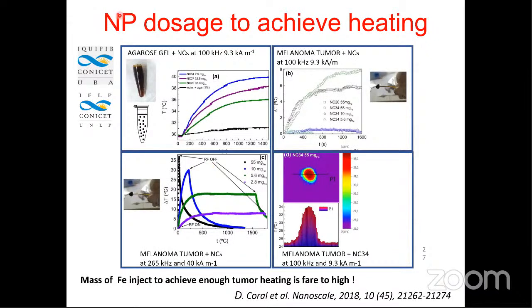And what we found is that, for instance, if we have an agarose gel with 2.3 milligrams of iron, we have a very nice increase of temperature. If we put this quantity in a tumor, we have no heating, and if we put twice this, we have no heating, and we have to increase the amount of nanoparticles up to 55 milligrams of iron. 55 milligrams of iron is a lot of iron. It's too much iron. If you remember the numbers I told you when I asked why iron, you will find that this is too much iron.